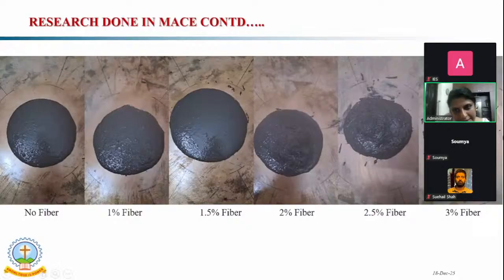Then this is what I said earlier. If you are increasing the dosage of fiber, that will enhance the properties of the UHPC, but that will negatively impact the workability. Negatively impact means there will be fiber agglomeration. There will be no proper dispersion of the fibers, and without proper dispersion of the fibers, we cannot get good results. So from this, this is the 20 mm straight steel fiber. From this only we have adopted, by considering both criteria: the compressive strength and the flowability. In the case of flowability, the 1.5% shows better results, better dispersion of fibers.